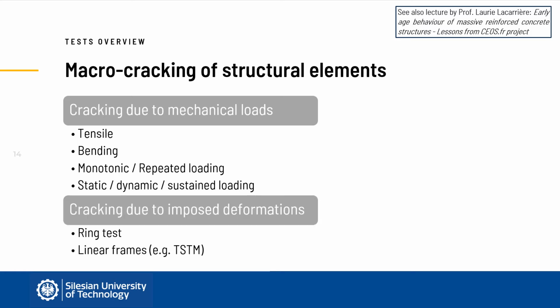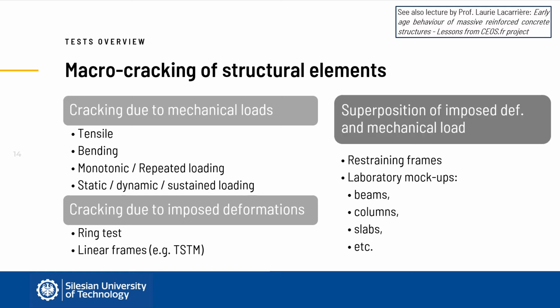When concrete elements are subjected to the action of imposed deformation, their cracking resistance can be controlled with the tests of restraint deformations, including ring tests and linear frames, for example temperature stress testing machine. If cracking can be caused by superposition of mechanical loads and imposed deformations, the isolated elements or even parts of the structure can be mocked up in the real scale. In this case, it is essential that the actual support conditions are properly represented in the isolated tests.